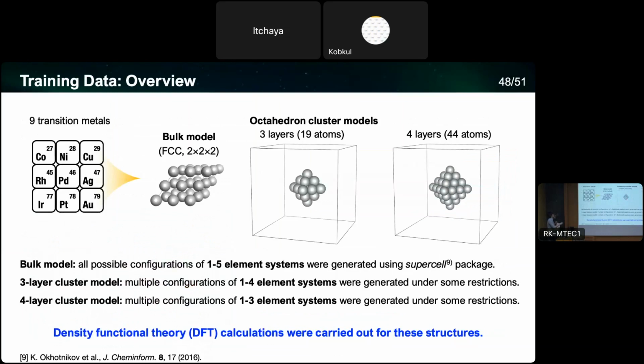So here is the overview of our training dataset. Our elements are these 9 elements. This is actually the same combination that was started with the Philippine group, one of our collaborators. So from copper to gold, we are dealing with these 9 elements. And the models that we are considering are this bulk model, FCC 2x2x2, and also these cluster models approximating the nanoparticles. The smaller one we call 3 layers, including 19 atoms inside the cluster. And the larger one we call 4 layers clusters, consisting of 44 atoms.